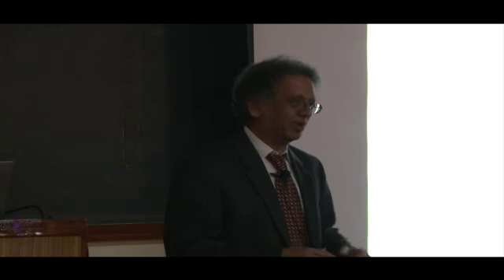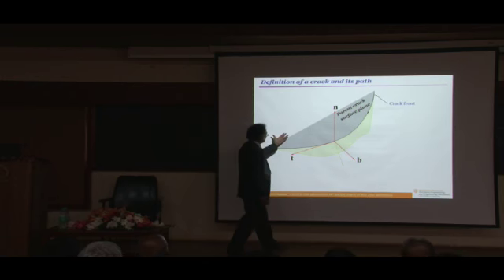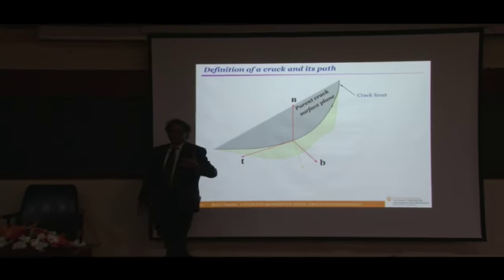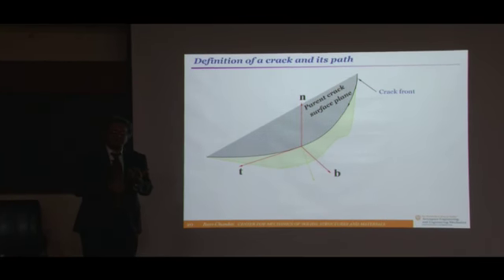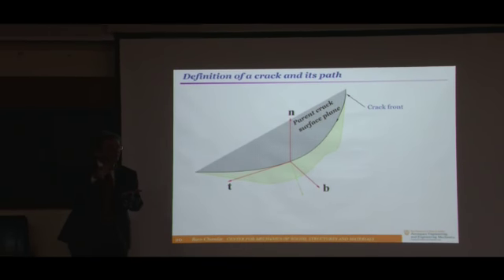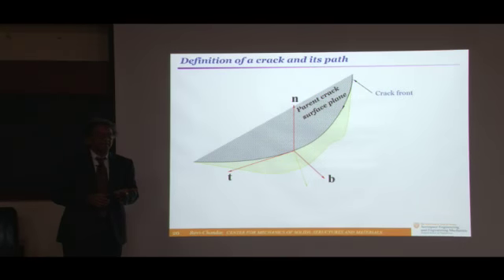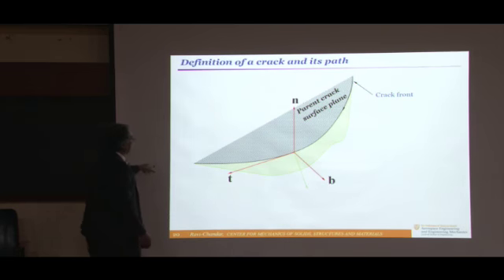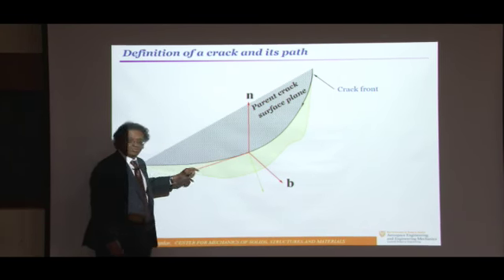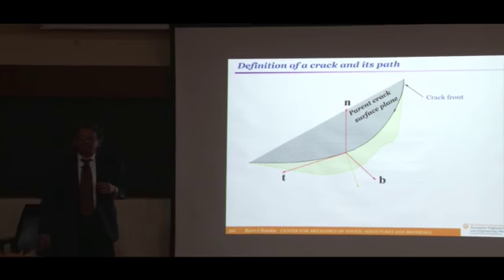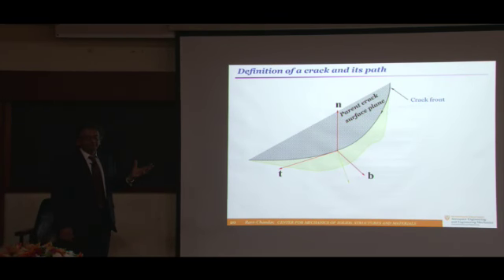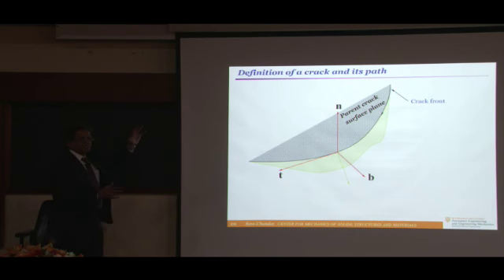The front, as you apply forces on the outside, may be able to move and evolve with loading. And this green shaded plane is my imagined evolution of the crack as you apply the load. So the question is, what minimum things do you need in order to define how this surface is going to evolve? I've put in a triad of unit vectors: T indicating the tangent, N normal to the surface of the crack, and B the other normal. It is not the Frenet triad. The N and the B are switched. But I want the normal to be perpendicular to the surface of the crack at every point.